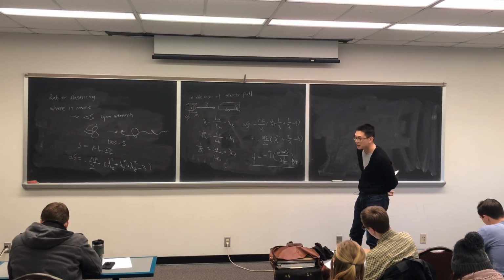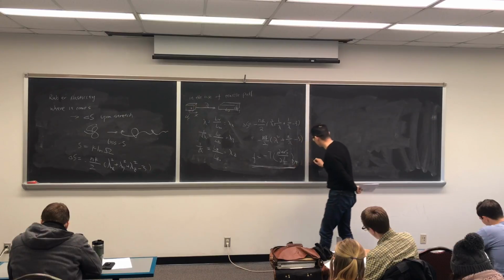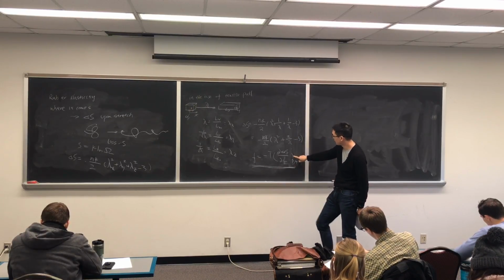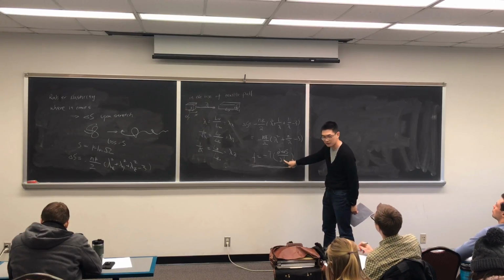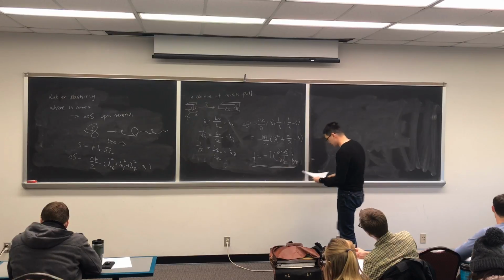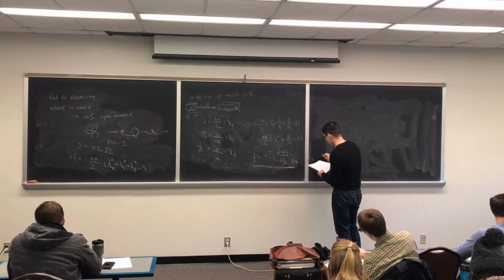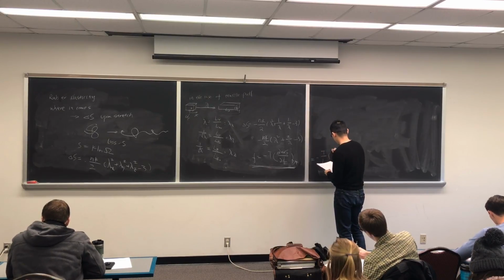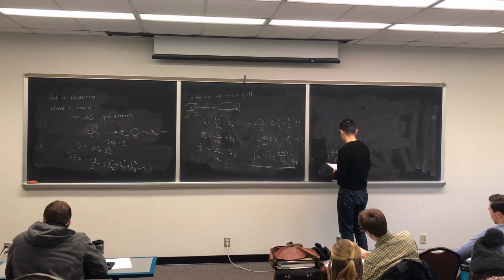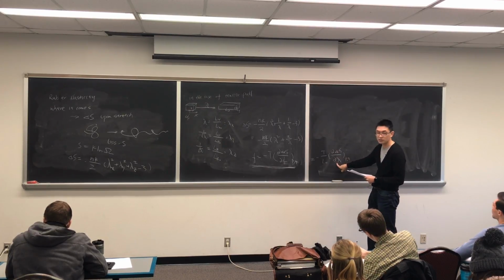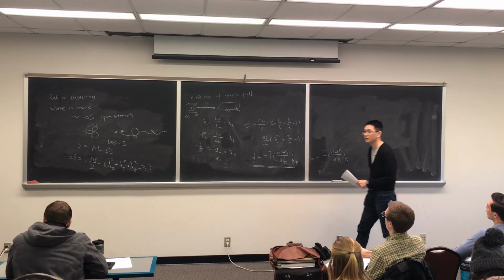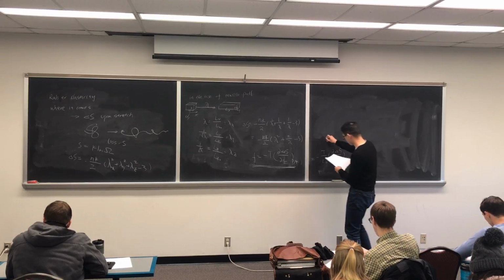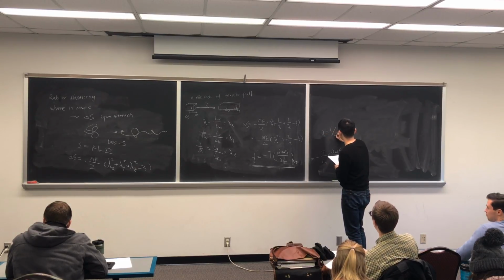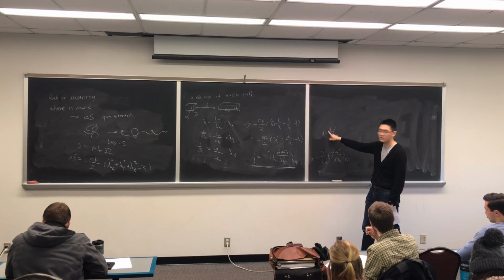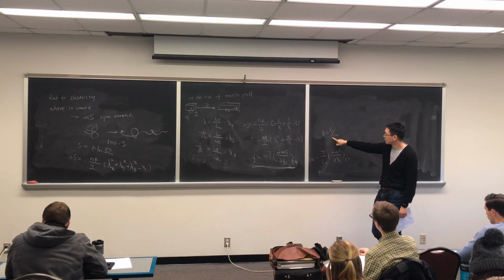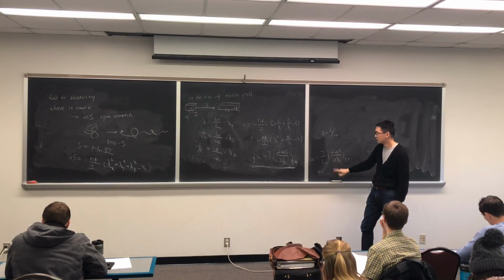So where we almost ended up in the last class, but we had a little bit more time, we did a partial derivative of this equation, where L is related to lambda. I won't go into too much detail, but we can first convert this to a partial derivative of lambda instead of L. The relationship is lambda is L divided by L0. That's the draw ratio, L is your final length, L0 is your original length. And if you take a derivative of lambda, you can convert it this way.